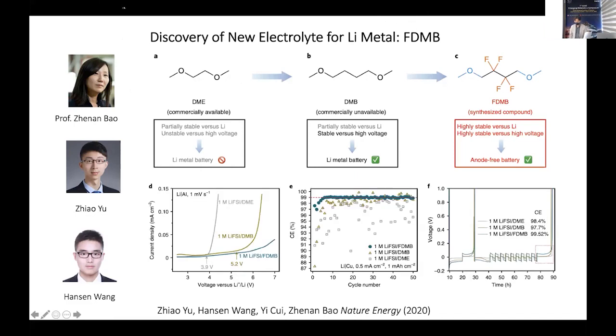If you look at figure D right here, using FDMB as the solvent with LiFSI salt, you scan to the high voltage on the cathode side. It's strongly resistant to oxidation, and becomes a lot more stable. Now used as an anode, that's figure E. The Coulombic efficiency, where you deposit capacity and then strip it away, becomes much higher. It becomes one of the record-type performances for an electrolyte. Using the so-called Aurbach method to cycle this, we discovered 99.5% Coulombic efficiency. It's a record high Coulombic efficiency.